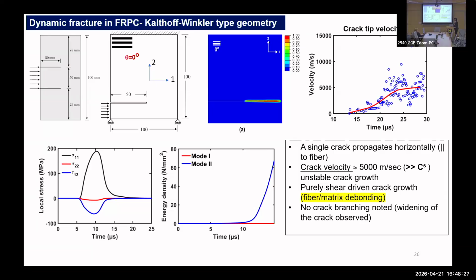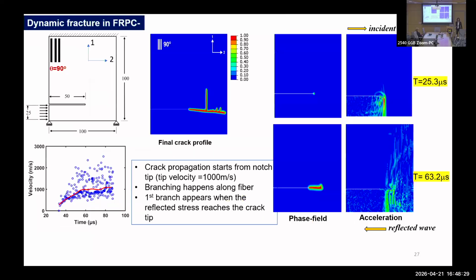Why I report here that we did not see any branching is because the moment we change the orientation to 90 degree, we now see a significant amount of branching as the crack tries to propagate horizontally. Again, same boundary conditions, only the fiber orientation is perpendicular now. We see that the velocity of this horizontal crack tip has dropped quite a bit compared to the 0 degree case. Branching tries to happen parallel to the fiber direction.